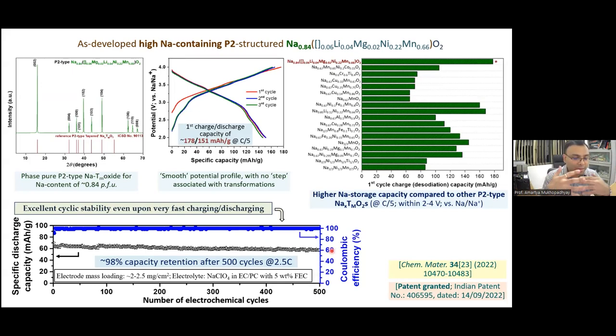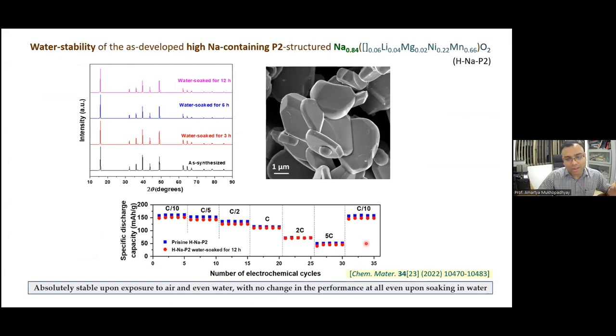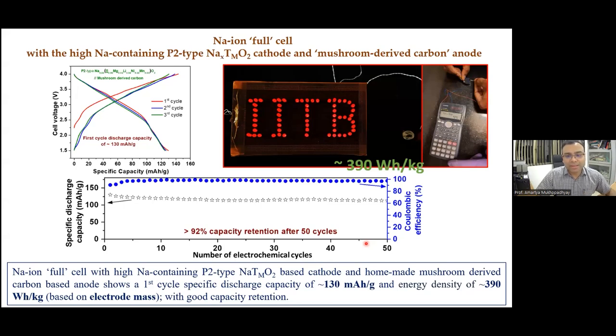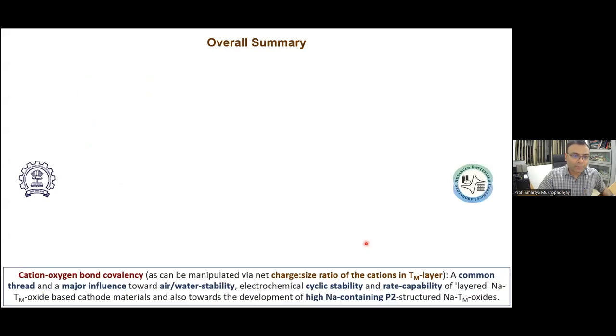So now this leads to a concept or an idea of how to make high sodium containing P2 type layered transition metal oxides, and it also showcases one of the P2 type structure materials developed in our lab, which shows exceptional cyclic stability and a good sodium storage capacity. And that material is also air and water stable because, due to the high sodium content, the interslab spacing is narrower, so the spontaneous sodium extraction is suppressed. So this material is also air and water stable. Again, as we do for some of the good results that we obtain at laboratory scale, we are progressing towards development of a full cell and eventually a prototype, which should be a good development.